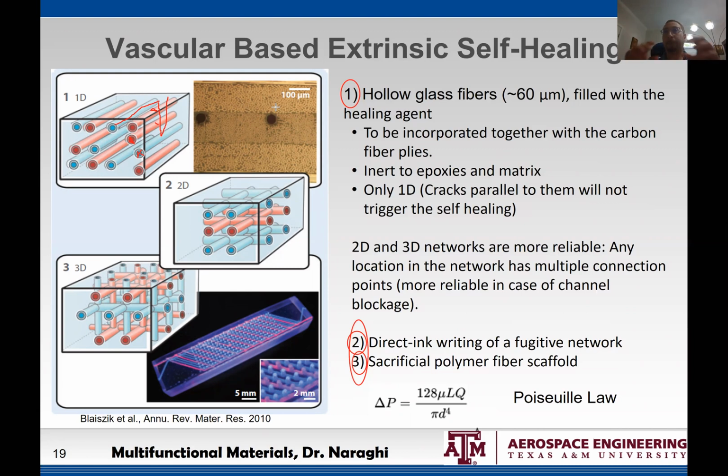Initially, the composite is liquid. I put the fiber in, I cure everything, then I get rid of that fiber. And so in place of the fiber, now there's a hole. The boundary is the matrix itself that has now solidified. These fibers are different from carbon fibers or glass fibers that are used for reinforcement. These are sacrificial fibers, just an example.